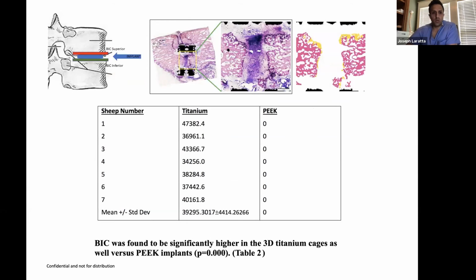The next thing we looked at was bone implant contact, which I think is important for early osseointegration, kind of this spot welding to the cage to get early stability. And what we found was that, as you could see in the PEEK cage, there was really no bone implant contact at all, but there was significantly more in the 3D printed biomimetic titanium.